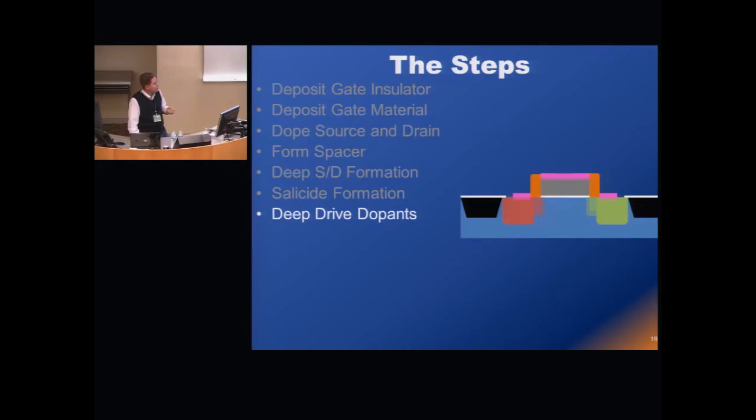Then you heat it up. You heat it up for two reasons. One, you're creating a stronger version of those salicides, and you're also moving the dopants around. Every time you heat the wafer up, you have to think about it. The law of diffusion applies, and you all learned the law of diffusion, I'm sure. And so the dopants, the impurities that you put in, will move around. So there's a thermal budget as you're designing this process, as you're designing this wafer. I can put the impurities where I want to start, but they're going to end up in a very, very different place in a very, very different concentration. So they'll deposit them, say, in the top corner away from the gate, and then they allow for the fact that all the subsequent processes will slightly move them closer and closer to the net result at the end of line, having all those impurities where you want, so your transistor behaves electrically like you would like it to.